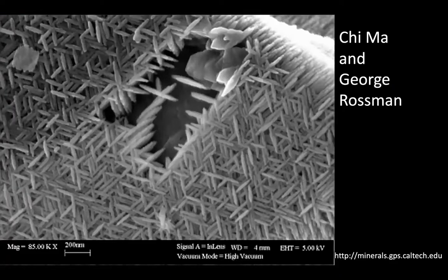The first efforts to study the causes of iridescence in hematite were done by Chi Ma and George Rossman, again at Caltech. In the 1990s, they analyzed this material with a scanning electron microscope, and they saw this striking pattern of spindle-shaped crystals oriented at 120-degree angles relative to each other. And they observed that there was an aluminum and phosphorus signal in their energy dispersive spectroscopy analyses. And they inferred that they were looking at some kind of aluminum phosphate mineral that had never been described before.